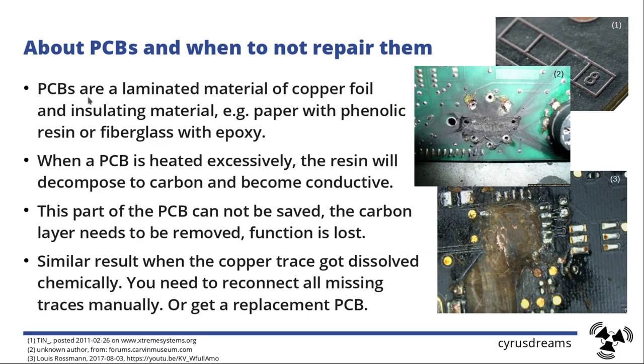Let's just have a quick word on what a PCB actually is. It's a laminated material. You have the copper foils, which are 35 micrometers thick, something like that, or even thinner, sometimes thicker if you have high power rails going on. And you laminate it together with an insulating material, that is paper with phenolic resin, which would be FR2 type, or you have fiberglass with epoxy, which would be FR4 type. So those PCB examples are FR4 type.